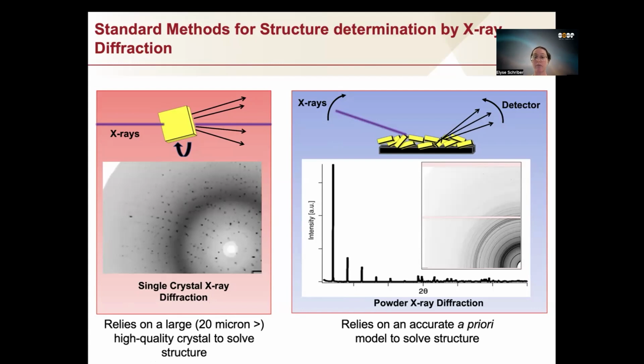The other option, if you have microcrystals or very small powders, is you can have microcrystals on some kind of substrate that are randomly oriented. So rather than rotating the crystal through the beam, the X-rays themselves and the detector are rotated so that you're able to collect every possible orientation of the crystal. And instead of getting spots, you actually get rings as we're sampling the crystal at all possible orientations. So rather than having the crystal be rotated and spots appearing and disappearing, every possible spot shows up in a ring-like formation. We can take a 1D radial average of this 2D image, and then we get a powder diffraction pattern.